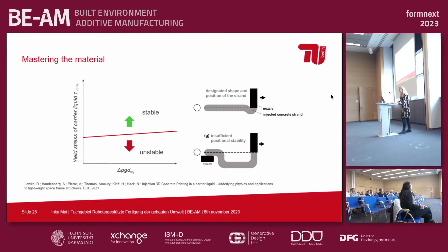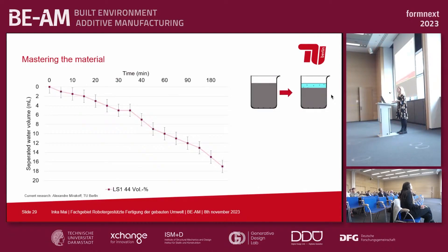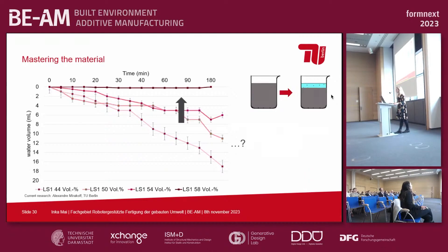It sounds like it is all solved, but this is also not the case at this point in time. You have to think about what is happening directly after injection of the material. The carrier liquid may also change over time. For example, if you are considering limestone powder suspension, you may experience significant sedimentation of the carrier liquid if not controlled correctly, meaning you are locally changing its properties. Locally changing material properties means you may experience a failure of the print at a later point in time. It is therefore important to master the material properties for a longer period.